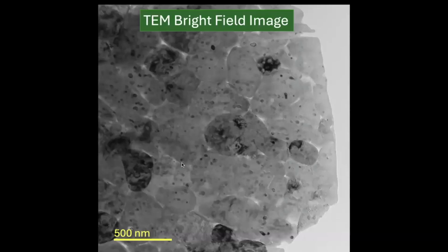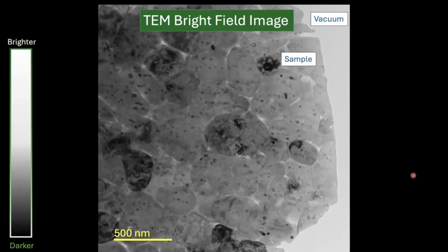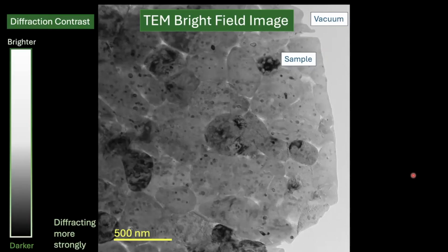So I'm going to introduce the types of images that I will be showing. This is a TEM bright field image with the objective aperture in. So this is like absorption or diffraction contrast. The vacuum here is bright, which is why this is called bright field imaging. Here's the scale of darker to brighter for diffraction contrast. Darker means it's diffracting more strongly. There are also contributions for higher average atomic number and thickness, but I would say it's mostly diffraction contrast.